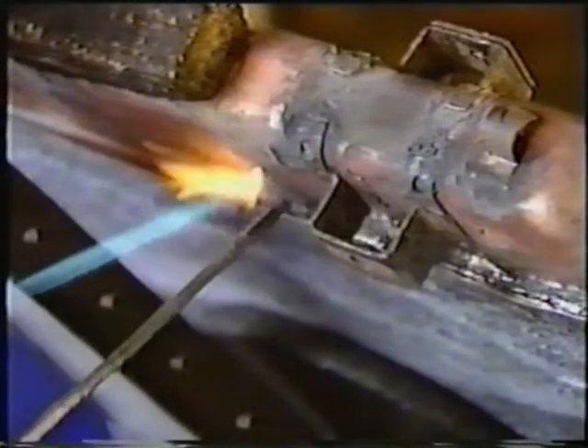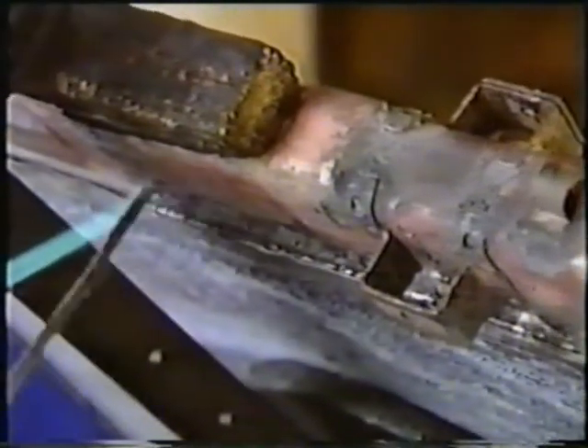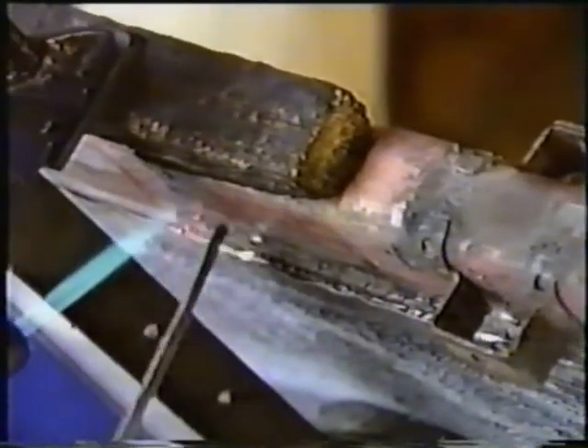And now let's follow the correct soldering sequence. Solder along this line from this side to this side. Turn the core around and then solder along the other side of the tank and header plate. Notice again the small flux brush. Notice the pencil-like flame, and notice how he is running the solder only along the bottom lip of the tank so that the solder runs down into the joint. Finally, finish off the ends.